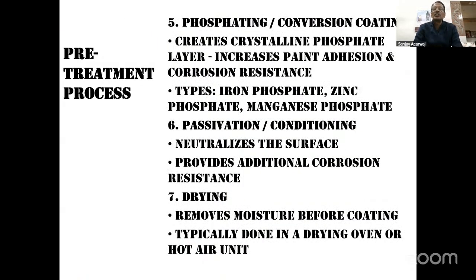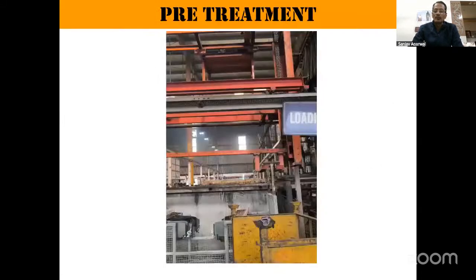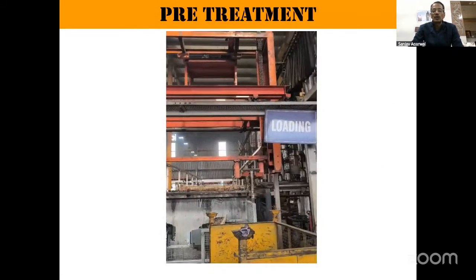Fifth is the phosphating operation. It creates a crystalline phosphate layer, increasing paint adhesion and corrosion resistance. The types are iron phosphating, zinc phosphating, and manganese phosphating. Then passive conditioning neutralizes the surface and provides additional corrosion resistance. Then we dry the part before painting, which we do in an oven. This is the pre-treatment process.